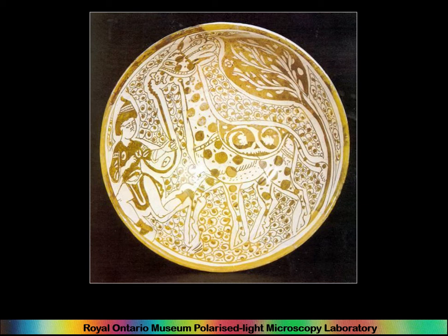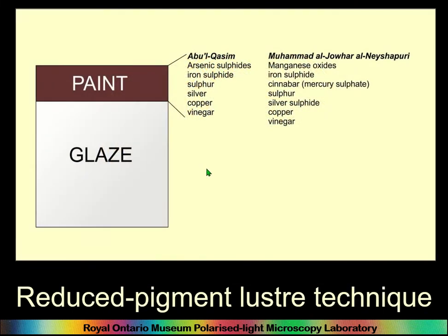And so they needed to make a body that worked really well with their glaze, because otherwise they couldn't make the lusterwares. I'm going to get around to explaining it. So the way you make lusterwares is we have a couple of treatises which tell you the sort of thing in it. The consistent things is you have silver and copper, and you create this paint with all this other stuff in it, like iron sulfides and arsenic and oxides and other stuff, vinegar, sulfur, and apply this paint.